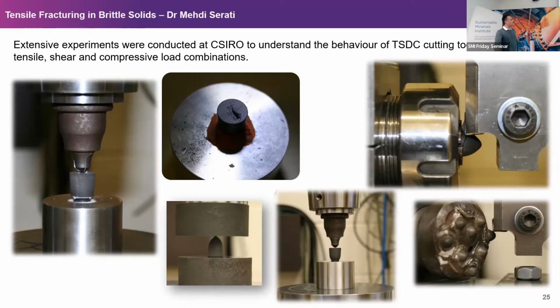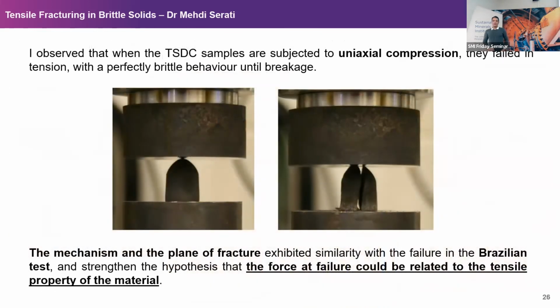Again, I'm showing these results, but it doesn't mean that I was involved directly in all of them. I had access. So we tested these TSDC cutting bits, which at the time were mainly available in bullet shape, as you can see, under different variations of load combination: compression, shear, tension. And then magic happens. If you have a bullet test and you measure the contact force, you can get the tensile crack. It's very similar to the Brazilian test, but of course with a different geometry.